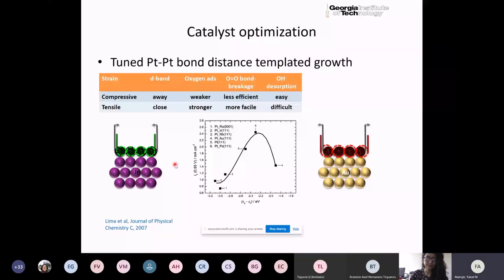That is, if you put material like iridium here with platinum on top, then because of the lattice mismatch, you're going to have slight compressive strain on the platinum, because the iridium atoms on average are a little bit smaller than the platinum atoms, and in order for the platinum to bond effectively with the iridium, they have to be squeezed together a little tighter. Alternatively, if you put gold as a substrate material and grow platinum on top, then you have the opposite effect. You have a tension, and that tension would essentially be pulling the platinum apart a little bit.